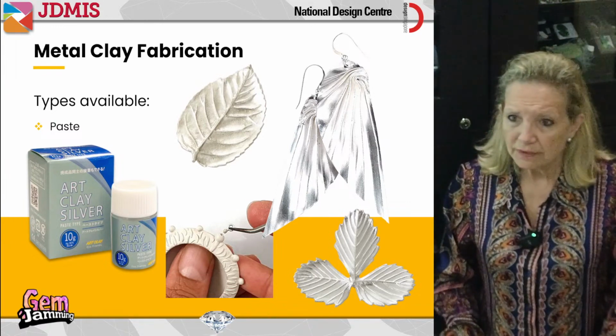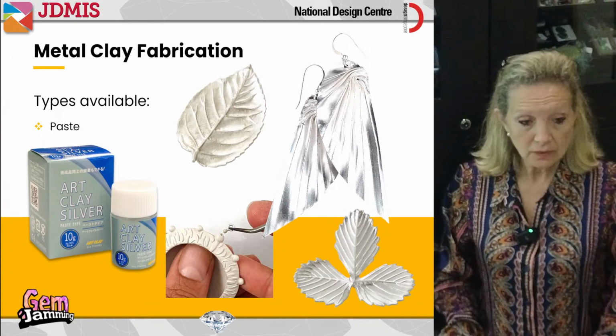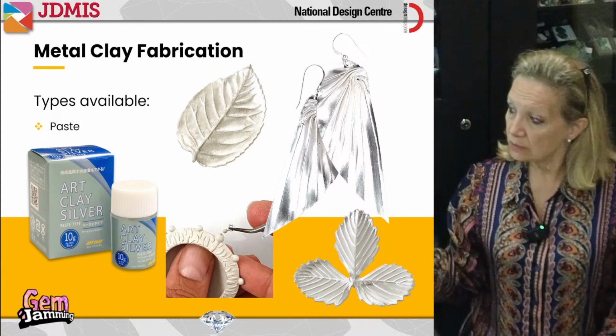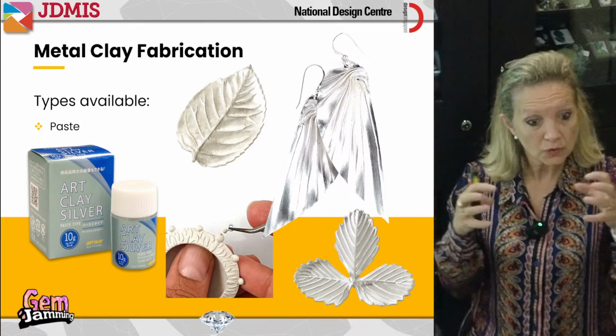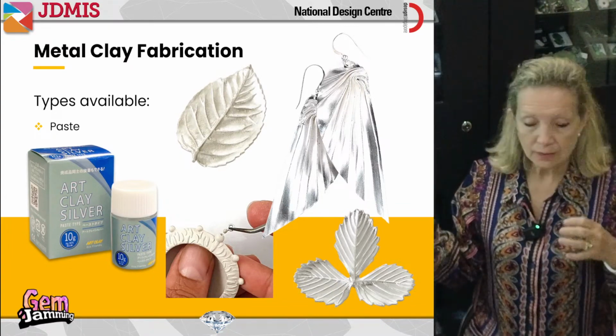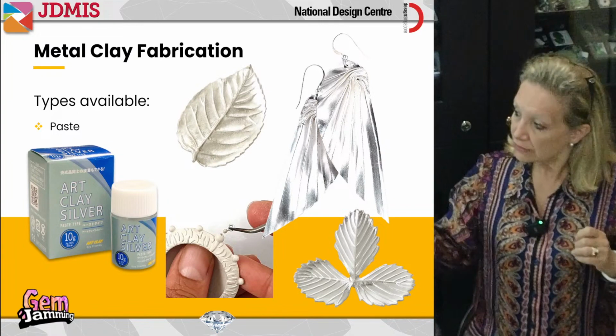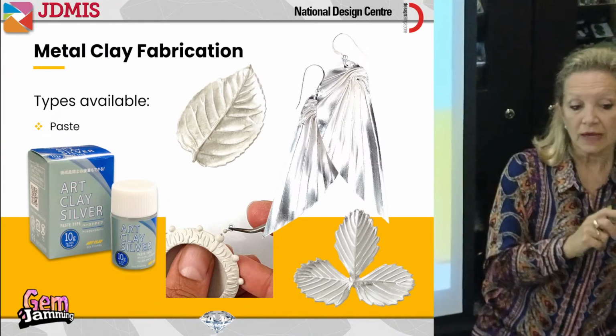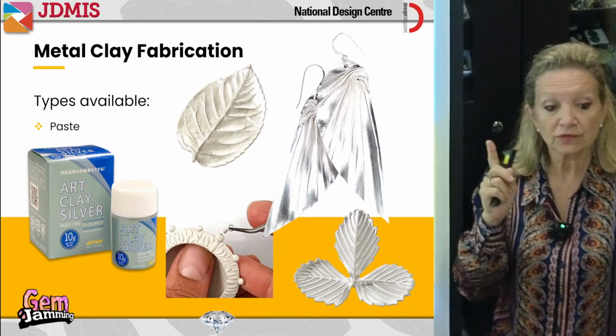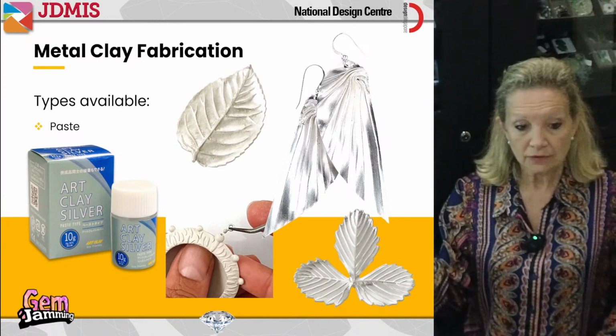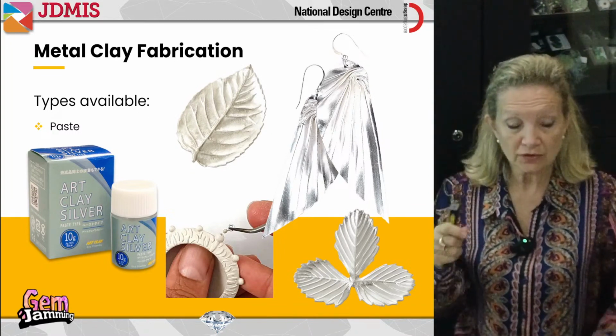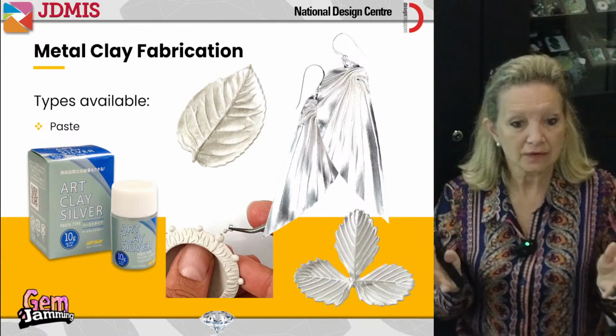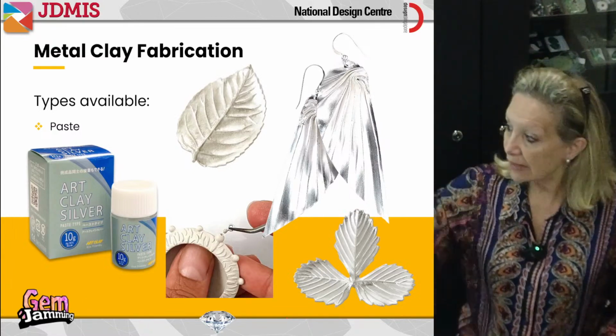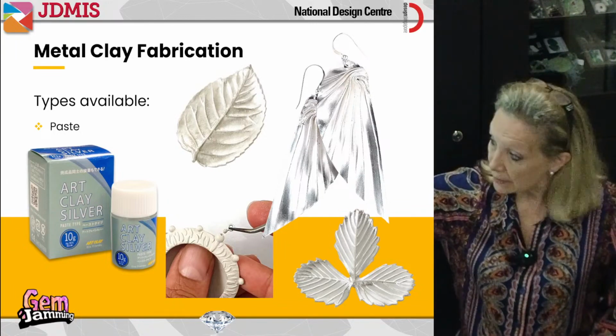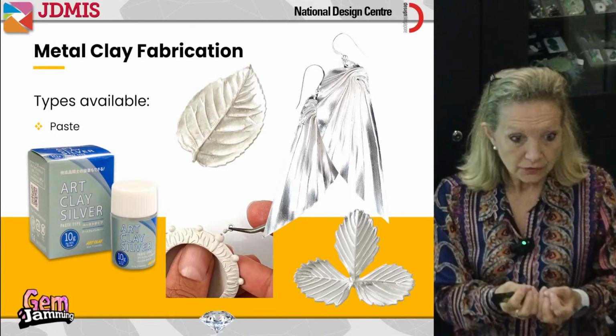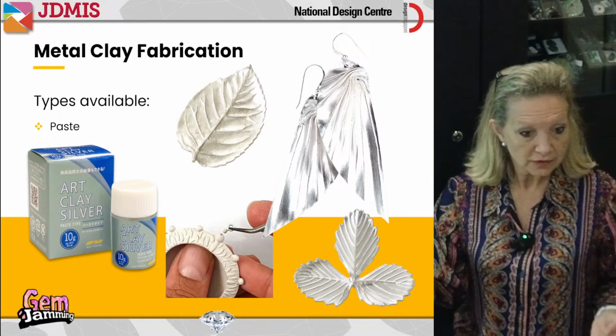What we need to be careful with is how the temperature is going to affect the other metal, because we know that the temperature is not going to affect our metal other than to cause it to sinter, and when it comes out white and clean and beautiful. But if I were to heat up, say that this little thing here was not 999 silver, we can buy them in 999 silver. What if it was 925 silver and then I heat it up? All right, those of you who do metal smithing, you know that when you heat up a piece of 925 silver, the copper comes to the surface and then it turns black. So we get oxidization. And that would happen if that little piece was a 925, but my original piece is still going to be very clean. So could I put the thing in pickle to clean off the oxidization? Yes, I definitely can.